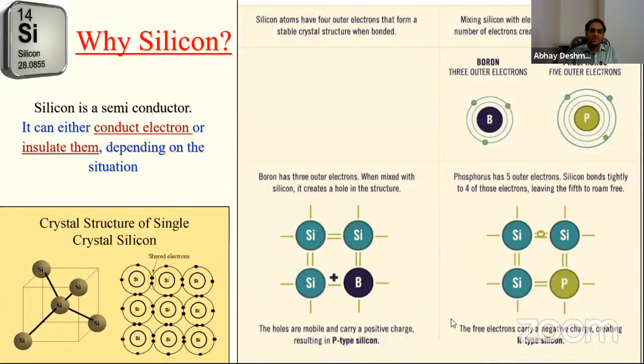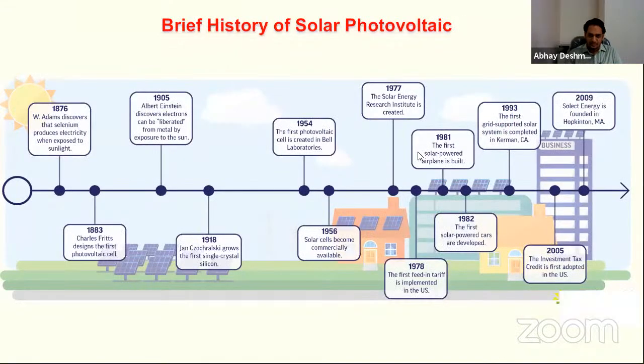So if you dope boron, which has 3 outer electrons, when we mix it with silicon, it creates a hole in the structure. And if you dope phosphorus, which has 5 outer electrons, then when you dope phosphorus in silicon, you'll have one free electron which will roam around. So boron-doped silicon we call p-type silicon, and if you dope phosphorus, we call it n-type silicon. And if you combine these two materials together, what we get is a p-n junction diode, right, which is responsible for generating the electrons and holes.